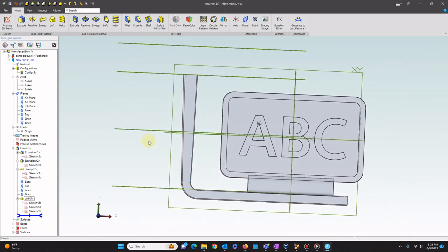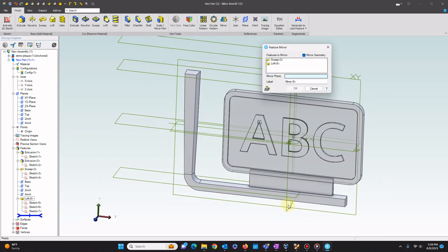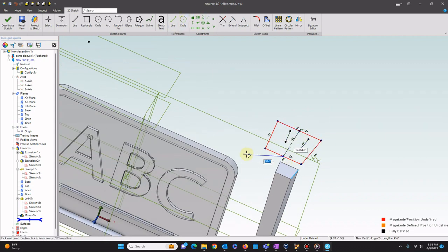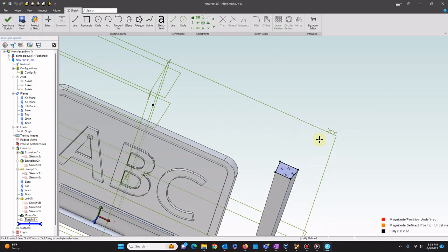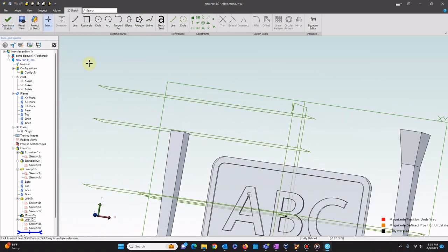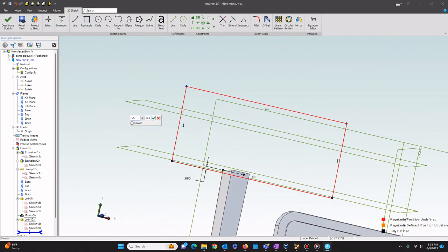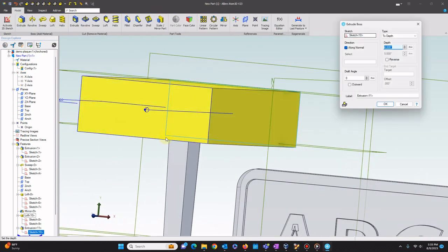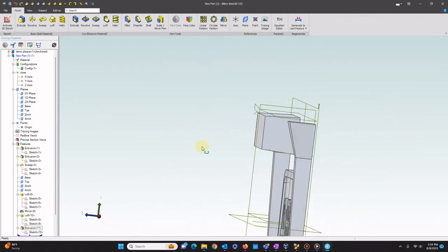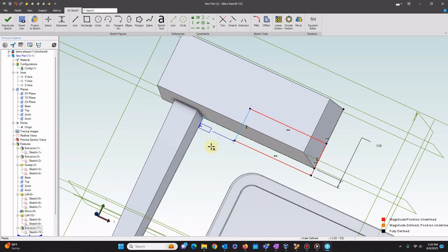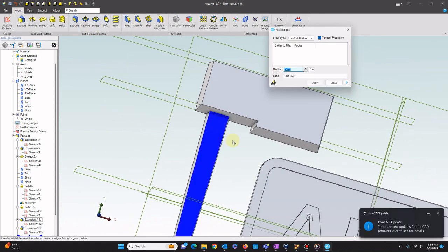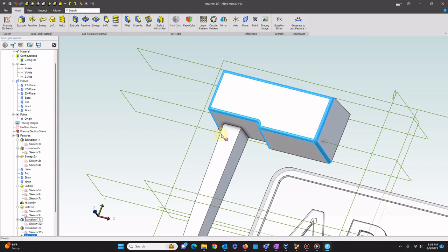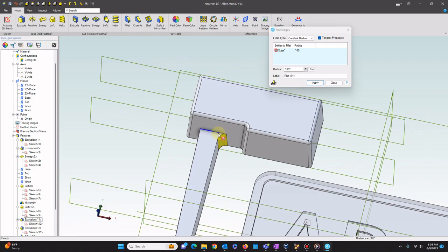With the runner transition and sprue done, we can make most of the surge trap just by mirroring these two features. Now we can loft to the surge trap to the top of the mold. This is not strictly necessary, but the surge trap does need to be vented and this will help align the running system pattern in the flask. Finally, we model the offset and stepped pouring basin. This step ensures that the initial splash of metal is kept away from the sprue. The pouring basin should be as large as practical. The larger it is, the easier it will be to pour the metal in and control the liquid level. Generous fillets around the top of the sprue are essential to prevent turbulence as the metal drains from the pouring basin.